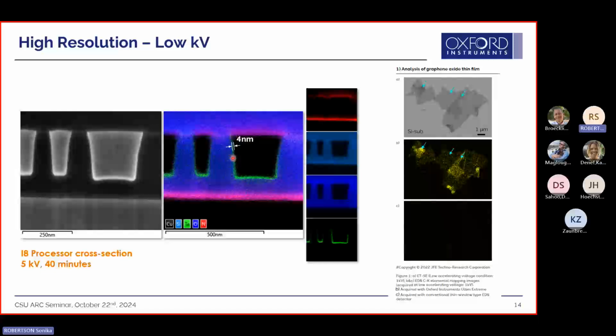So when you remove that with the windowless, this is a processor cross-section, and you can see this layer. Granted, it's tantalum, it's heavier. It's still 4 nanometers wide, and this magenta color here, this is actually the nitrogen layer. So that's the lighter element that you're seeing. Scale bar, 500 nanometers here.